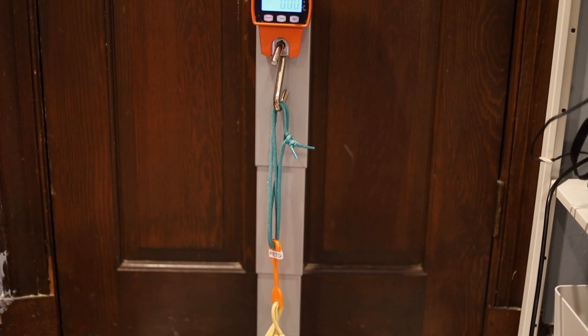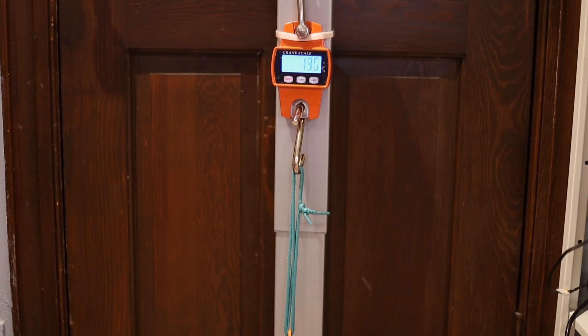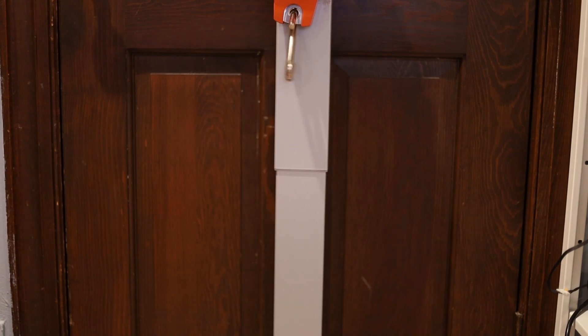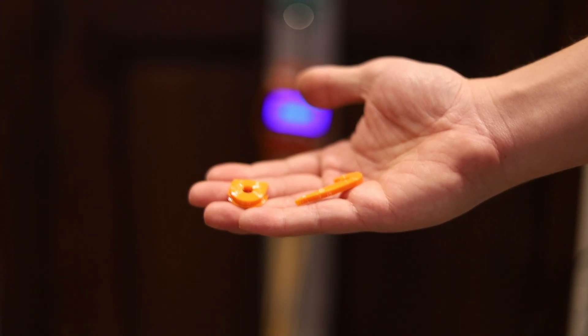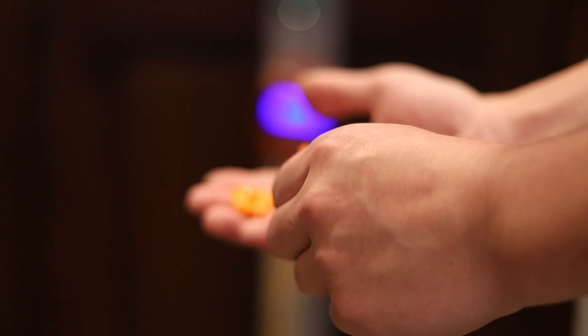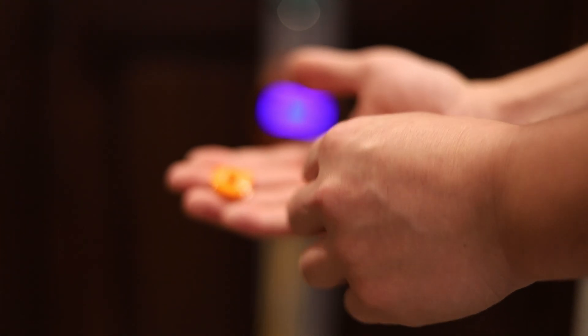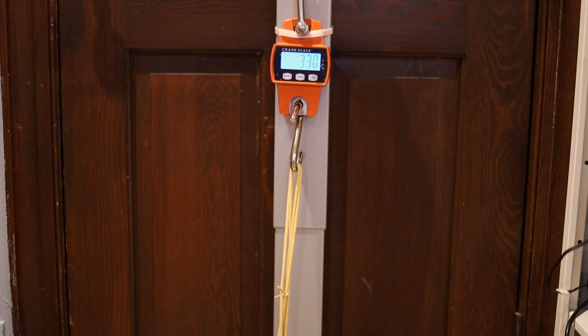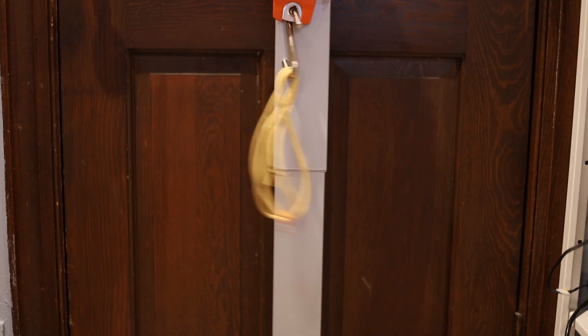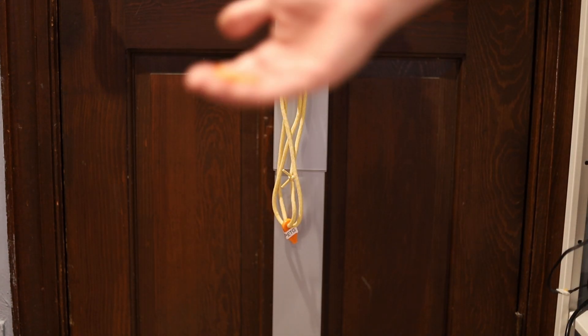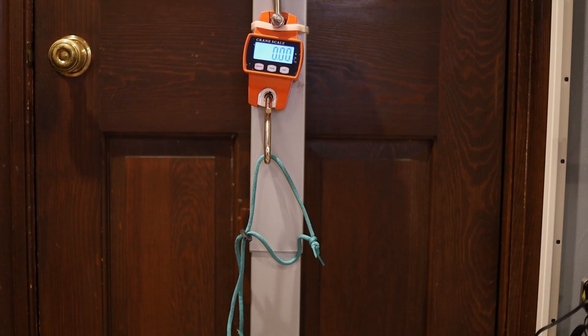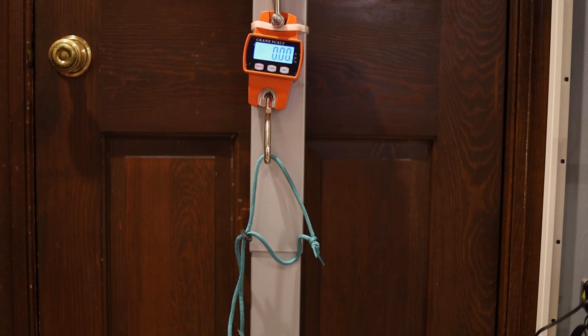I'm going to do one more test with the PETG. That PETG sample completely shattered when it failed. That's indicative of a material with low toughness, like glass. Glass shatters, it's not a very tough material. I'll give PETG one more shot. We got another sample there. Wow, I'm finding shards of broken PETG all over the place. And that's a wrap. Time to put all the data together and review it, and see which one performed the best.